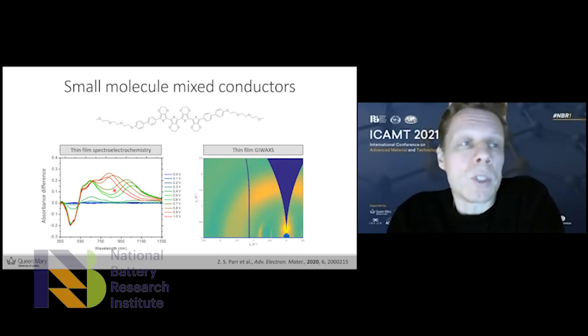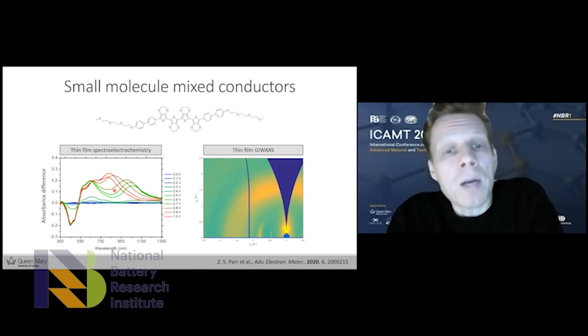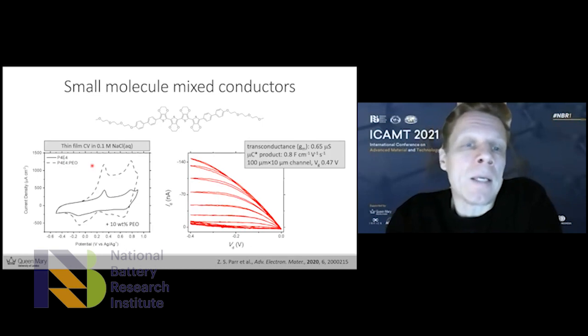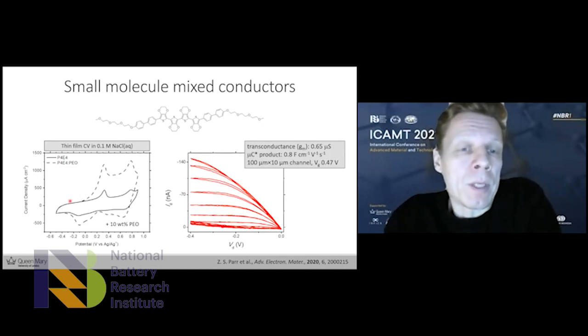So we do see the generation of charge carriers, which is promising. And again, in the thin film cyclic voltammetry experiment, we see nice and reversible oxidative behavior, again forming the radical cation, the polaron species, and subsequently the dication, the bipolaronic species.